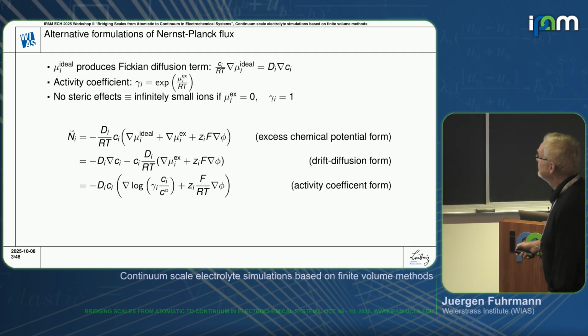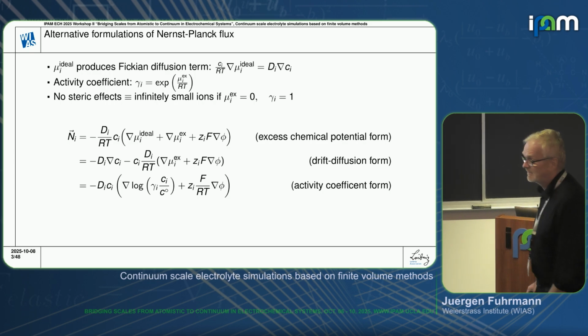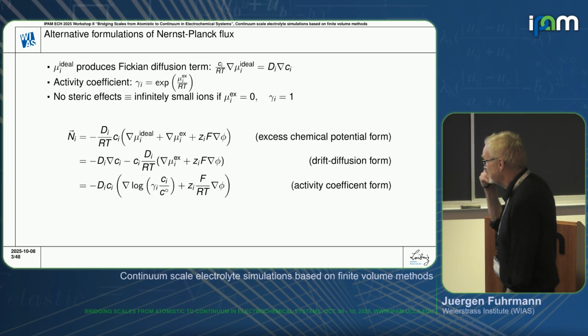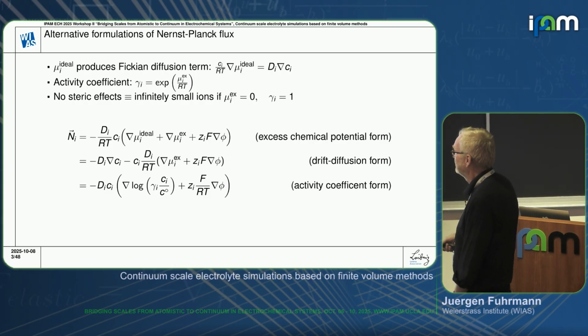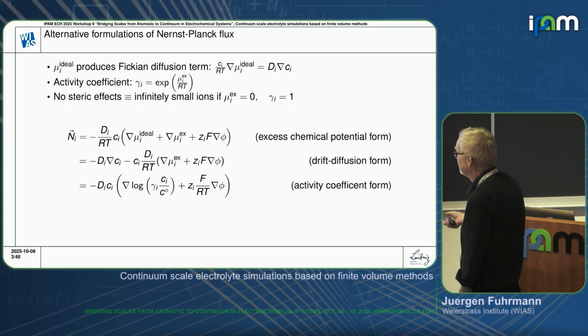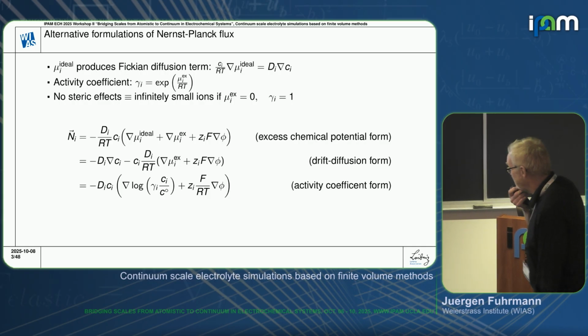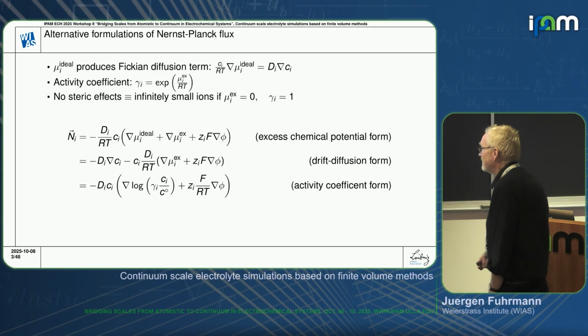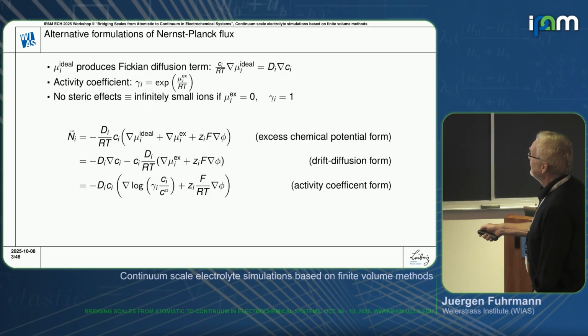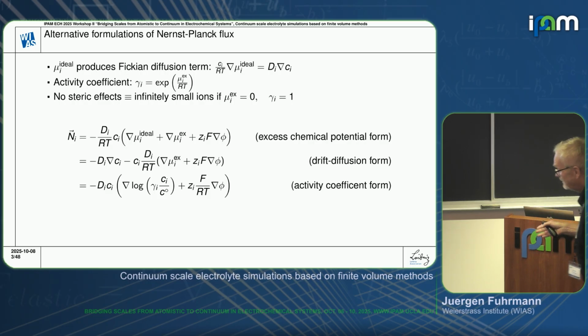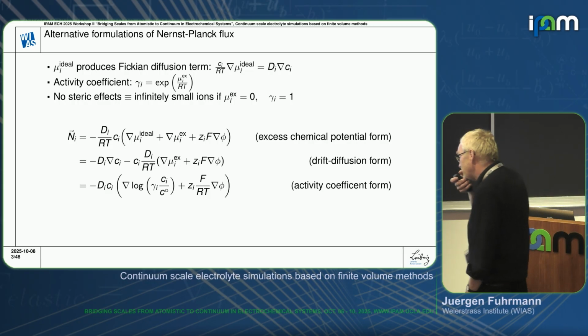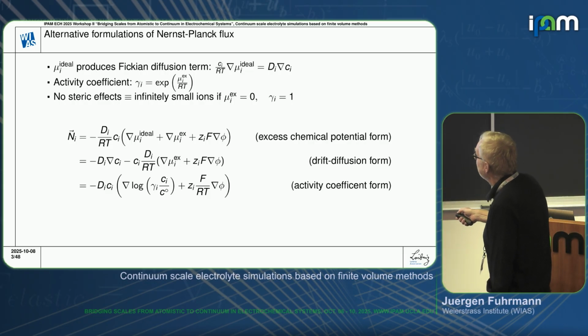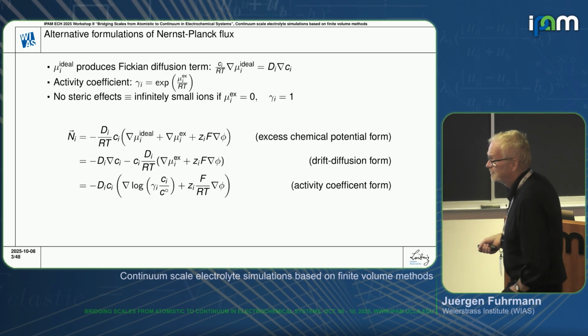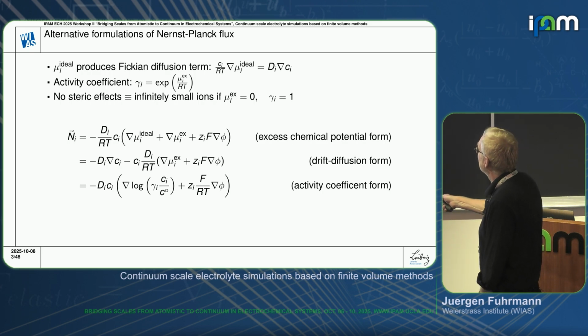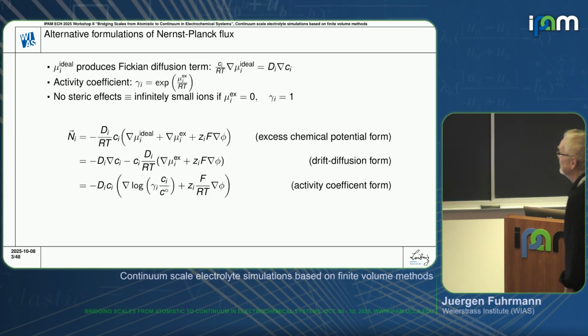So we can write these Nernst-Planck fluxes in different forms, which give rise to different inspirations for how to, for instance, discretize them or analyze them mathematically. First, we can see that the ideal gas contribution to the chemical potential gradient gives us the classical Fickian diffusion term, where the movement of species would be driven by the concentration gradient.